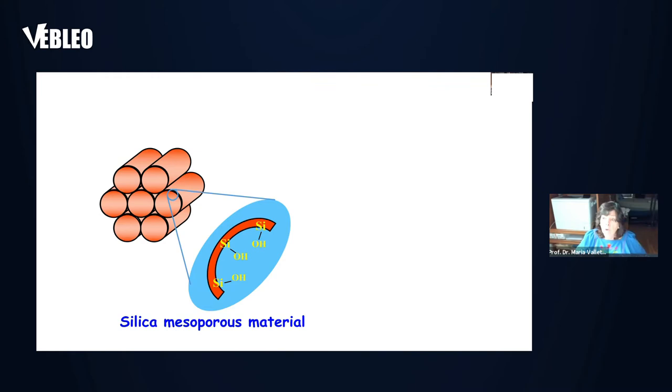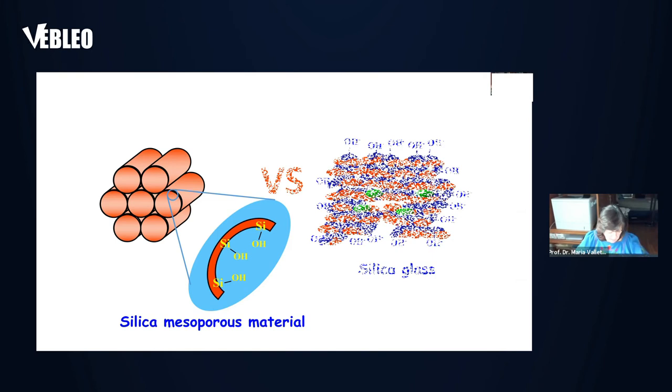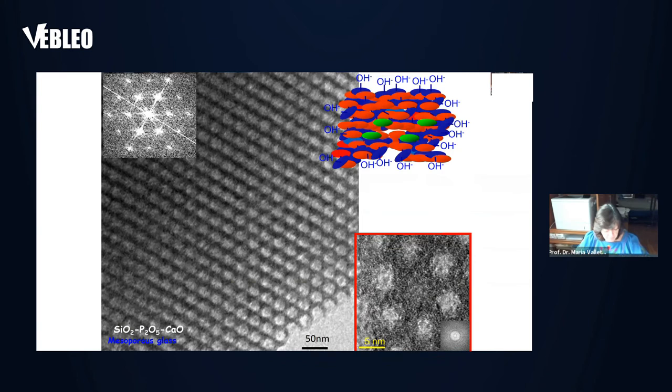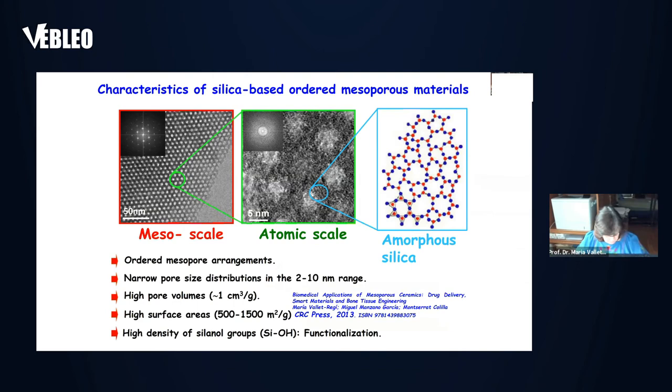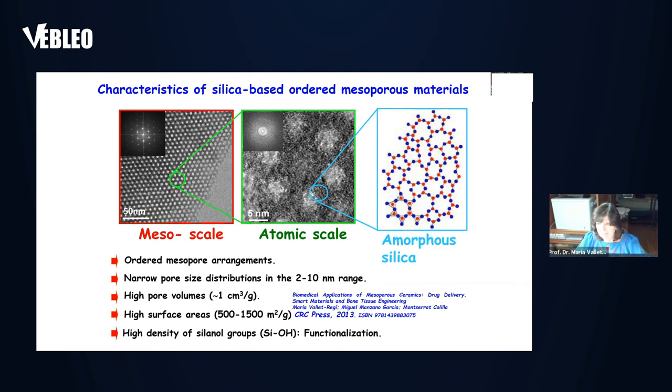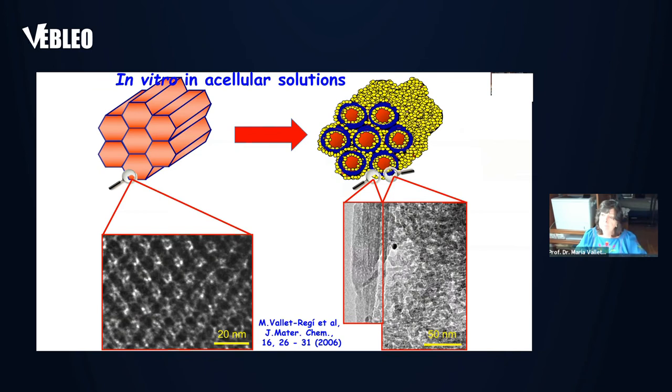Let us recall the presence of silanol groups on the walls of silica mesoporous materials. This is a common feature with bioactive glasses, which are materials used for bone substitution. But the main difference is that they exhibit an ordered mesostructure. They are amorphous materials, but with an ordered arrangement. In short, a large specific surface, a large number of silanol groups on the surface, and a large controllable pore volume combined with ordered mesostructure are all positive factors for devising multiple chemical choices to modify these materials in the desired direction. They are biocompatible and bioactive.